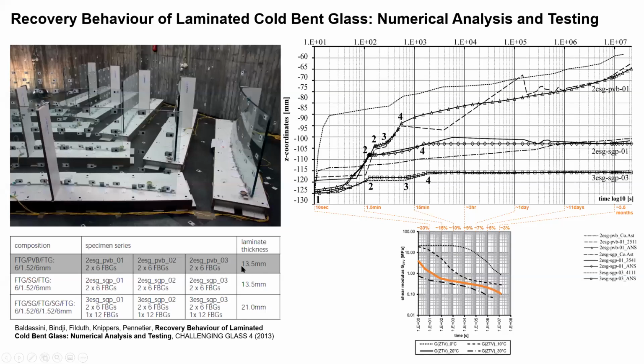We looked at multiple types of laminates using PVB, SGP with 2 or 3 plies. And so as you see in this graphic, the loss of stiffness of the interlayer has a reciprocal effect in a flattening of those compounds. So again, these were fabricated in cold bend technique. This is what people call laminated laminate bending. So basically, we were just looking at the interlayers to keep the shape.